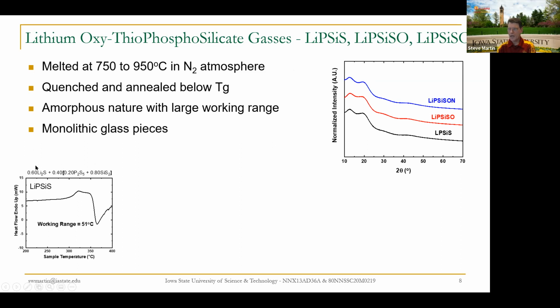The compositions are kind of complicated, but if you think of lithium sulfide as sodium chloride, and you think of these things out here as water, it's really just sodium chloride dissolved in water, except now the phosphorus sulfide and silicon sulfide, that's more of a liquid that we quench to a glass. But it turns the otherwise insulating phosphorus sulfide and silicon sulfide, like H2O, except for a little bit of ionization, it turns the otherwise insulating network structure of the glass into a lithium ion conductor. We're interested in glasses, so we quench them to glasses.